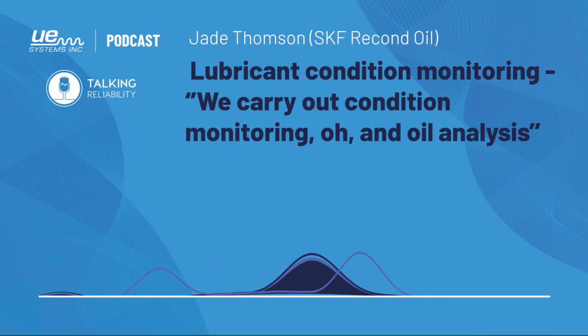If we look back at the one we've just looked at for a failure, that was a conflict between two oils. It was a massive incompatibility issue. If we know which oil should be in there, we can diagnose something like that happening really quickly. Someone could just be topping up 5 litres a week with the wrong oil, and it might take a while to become catastrophic. If the lab know that as soon as possible, we can catch it much earlier.